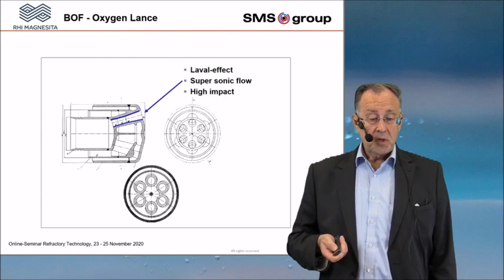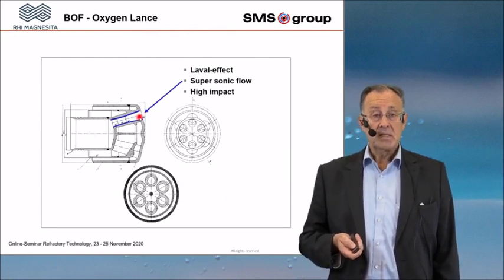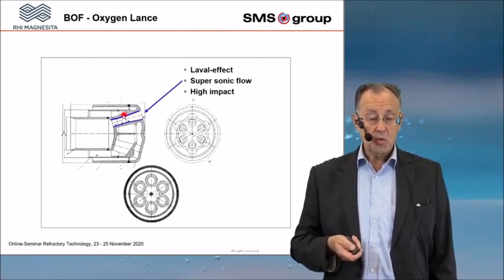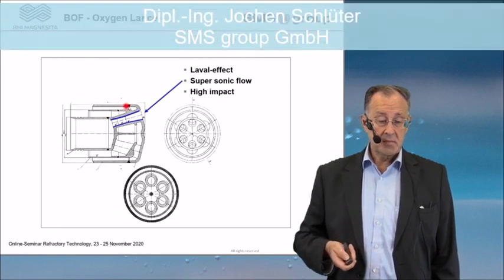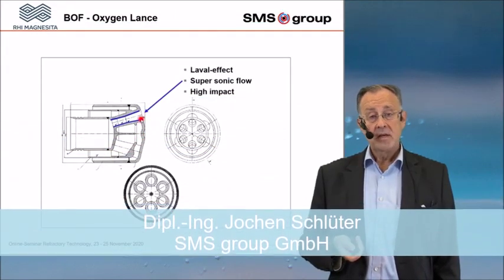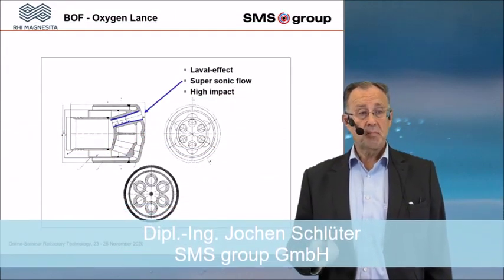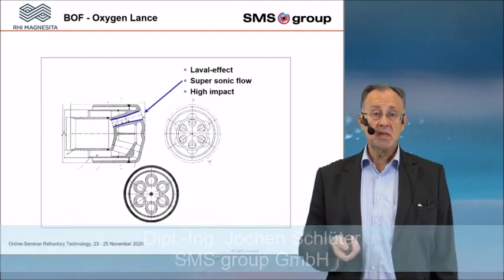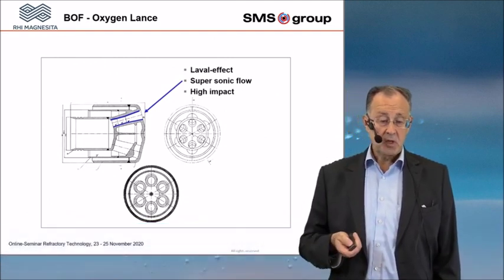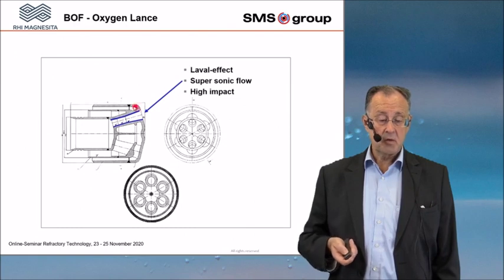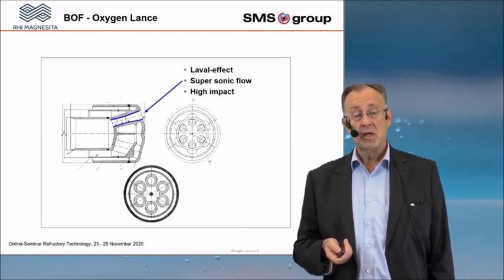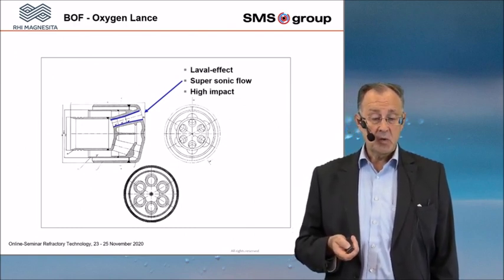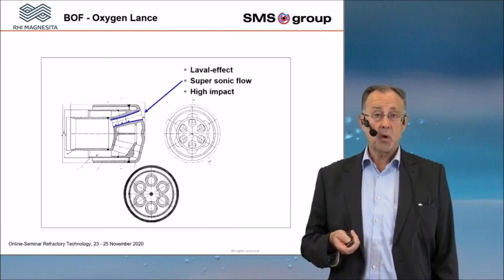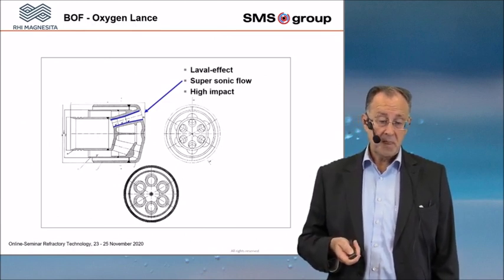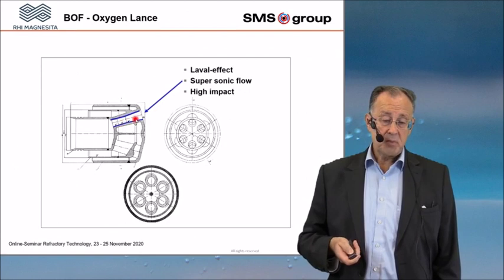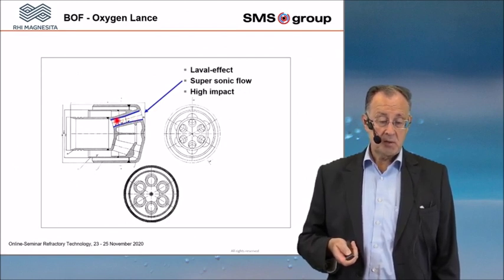One important point is the lance, and that means the lance tip. You have a water-cooled lance, and at the tip of the lance you have a copper lance tip. Why is it copper? Because you need a high heat transfer, because the lance is inside the converter in a very high temperature atmosphere, and you have to cool the lance to avoid that the lance will be destroyed. And one very important thing is the nozzle.